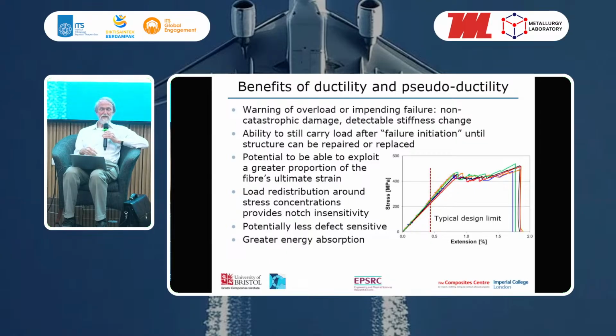So these composites then have the ability to still carry load after that failure initiation until the structure can be repaired or replaced. We've also got the potential to exploit a greater proportion of the fiber's ultimate strain. I didn't really talk about that, but by putting the hybrids together, we can actually achieve a higher strain than we could on their own. We do see some hybrid effect in both tension and compression, which means we can take greater advantage of the properties of the material. We also see load distribution around stress concentrations, which provides notch insensitivity, which is very good for avoiding failure from sharp cracks or holes or other stress concentrations. And potentially these materials should be less defect sensitive.